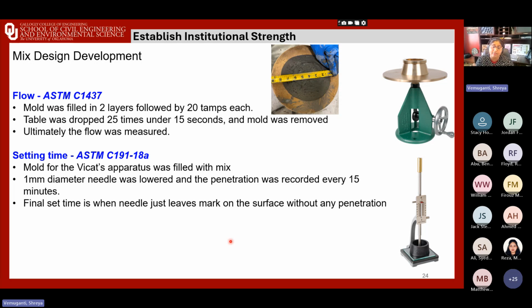You might have local materials, materials that are locally available to you. The gradation is different, the maximum aggregate size is different. So we have to ensure that the mix is developed first. So standard procedures were followed. You have ASTM C1437 for the flow, setting time C191. And these tests gave us early insights into how the material would perform with this nozzle extrusion and so on.